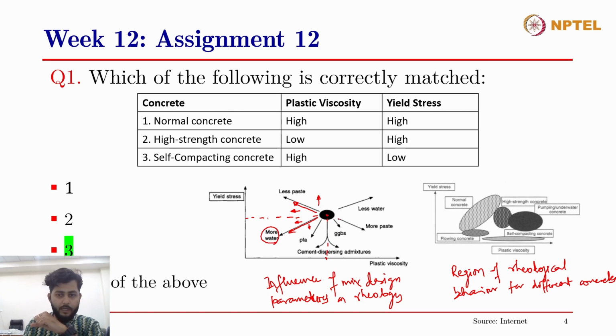Similarly, if you increase the paste content, the viscosity will increase and the yield stress will decrease. So the concrete will move this way, while the viscosity increases, because now you have added more cement to it. When you increase the paste content, you're increasing the cement and the water content alike, right? And when you're increasing the cement content, the probability of interactions between the cement solid particles will increase. When the probability of interactions increases, the network structure being built between the cement solids will strengthen more quickly and gain rigidity more quickly now.